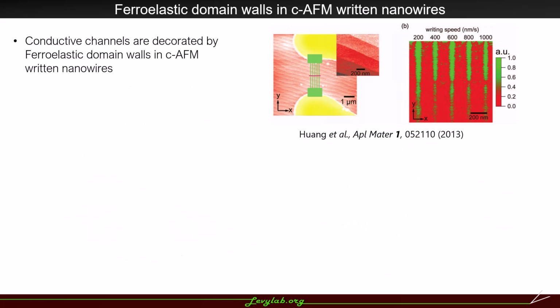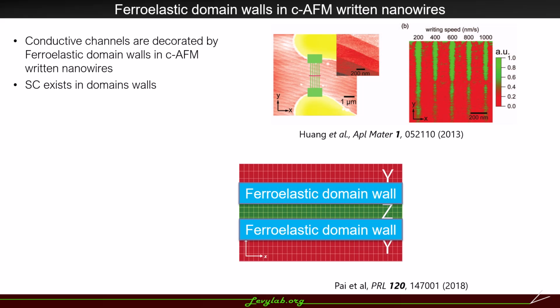Now we discuss the preliminary data in the context of ferroelastic domain hypothesis. Strontium titanate undergoes a cubic to tetragonal ferroelastic antiferrodistortive transition at 105 Kelvin, when X, Y, and Z domains can form. It has been demonstrated that the c-AFM written nanowires, the system that we're measuring, are elongated in Z direction at room temperature, seeding ferroelastic Z domains after that transition under 105 Kelvin. Outside of the conductive channels will be X or Y domains. It has been shown that superconductivity exists in the ferroelastic domain walls that decorate these conductive channel edges.